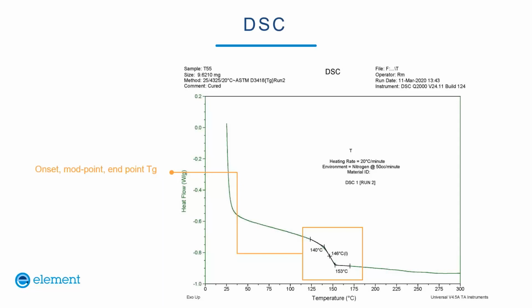This is an example of a DSC curve, and the area of interest is down here. We're heating it up, and then the amount of energy it takes to heat it up changes abruptly. And where it first changes is called the onset of the glass transition by DSC. And this is usually reported because it's most closely related to the loss of mechanical properties. But sometimes midpoint is called out, and sometimes even endpoint is called out. So the onset right here is, again, 140 degrees C.